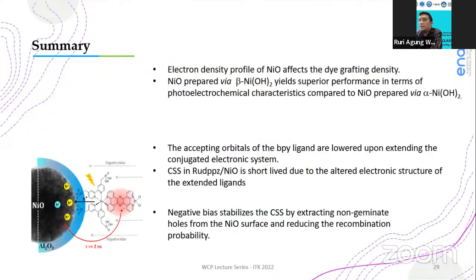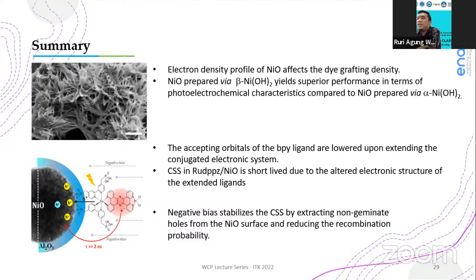So, to close the presentation, because the time is up, I will summarize what I talked about in the 3 different sections before. I have first shown that nickel oxide prepared from beta nickel hydroxide is preferable for photocatalysis in dye-sensitized photoelectrochemical cells because the electronic nature allows for covalent bonding with different anchoring groups of the sensitizer. And then from the second part of my presentation, I have shown that extending the conjugated electronic system lowers the accepting orbitals of the BP ligand. And this leads to a shorter charge separated state lifetime in the ruthenium DPPZ sensitized nickel oxide. And finally, if we apply negative bias at dye-sensitized nickel oxide, this enables stabilization of charge separated states by reducing the non-geminate recombination, and quite significantly prolongs the charge separated state lifetime.